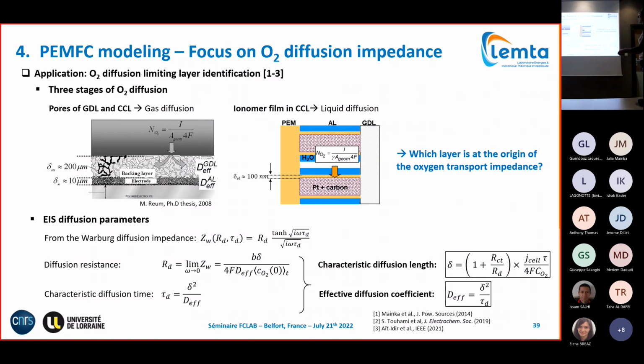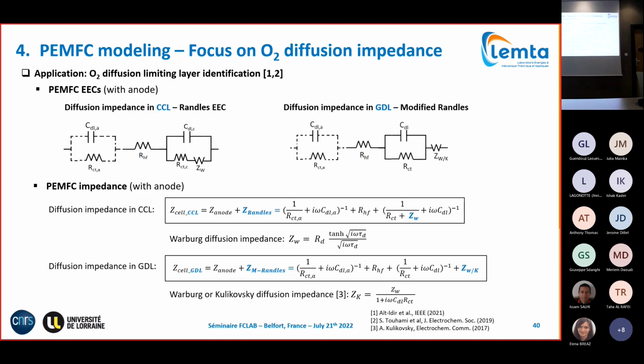And what you see here, they are linked to the characteristic diffusion parameters. That means from our electrical components, you can directly obtain the characteristic diffusion length and the effective diffusion coefficient. Just note that here it's characteristic diffusion length and coefficient, meaning it takes into account the porosity and the tortuosity. Just keep this in mind without going into detail. Here we show the different models we used to interpret our spectra.